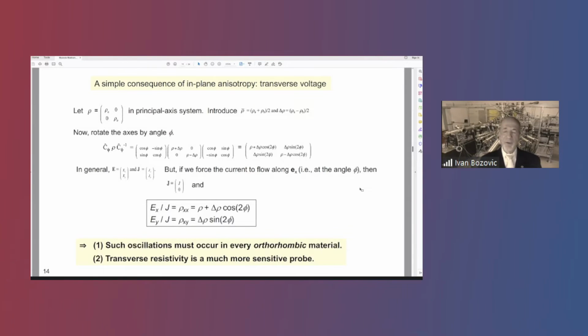And therefore, your signal-to-noise may not be good enough to pick up nematicity if the amplitude, if the difference between rho_a and rho_b, is small. On the other hand, the transverse resistivity will show that clearly, because if the crystal is tetragonal, then transverse voltage must be 0 by symmetry. As soon as you see non-zero transverse voltage, that indicates that the C4 symmetry is broken, that the crystal is not purely tetragonal.